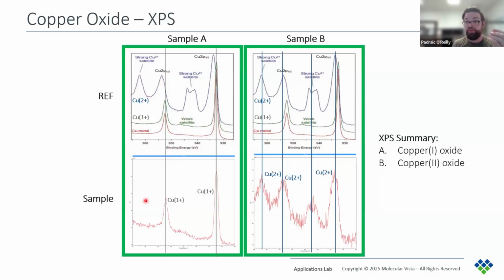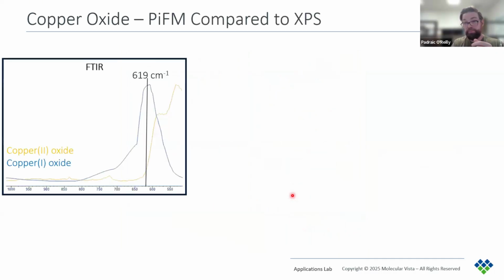Now, from looking at those taken on the sample, which is this bottom row, we see that sample A consists of copper-1 oxide and sample B of copper-2 oxide. So one of the limiting factors with XPS is its relatively poor lateral resolution, which is in the realm of microns. So therefore, XPS will not be able to investigate individual small pads, especially if they have small pitch sizes as well. So again, this is where PiFM can come in.